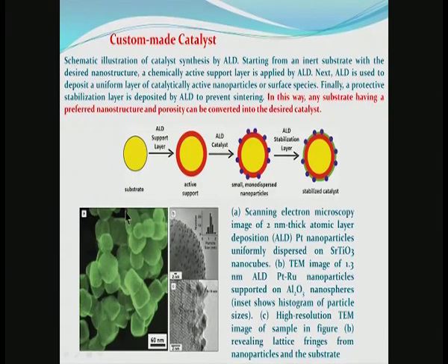What is shown here on the left in green is a high resolution scanning electron micrograph, and by the side of it are transmission electron micrographs of the same thing. What we have are cubes of strontium titanate. It is possible to obtain nanometric cubes of strontium titanate. Strontium titanate has a cubic structure and therefore, the morphology of cubes in nanostructures is natural for strontium titanate, although it is not easy to produce them.